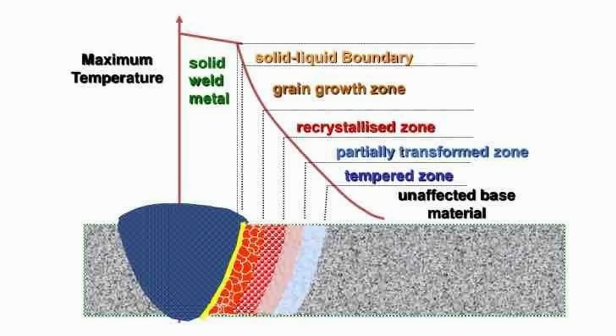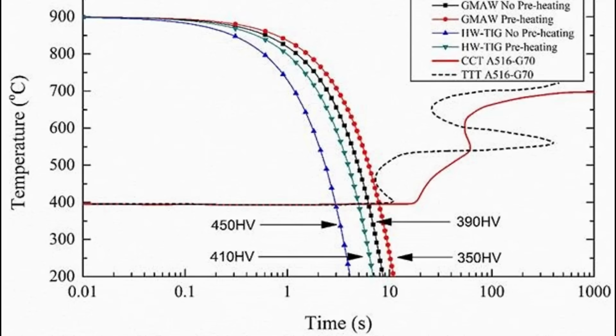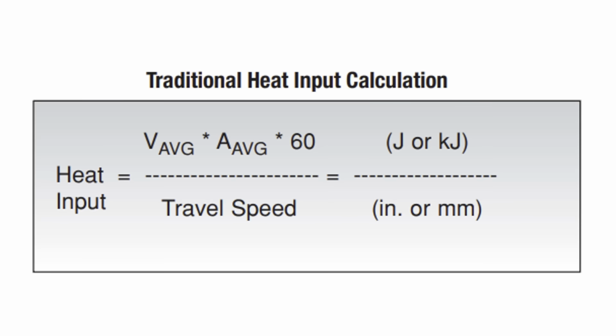If certain carbon steels, especially medium to high carbon steels, cool too quickly, you risk forming brittle structures that are susceptible to cracking. However, if certain stainless steels, like austenitic stainless steels, cool quickly, it is a good thing, while cooling too slowly can lead to significant problems such as sensitization. Engineers calculate these limits to ensure the finished weldment has the desired mechanical properties and resistance to weld failure. Understanding heat input helps you control the fundamental changes happening within the metal as you weld.